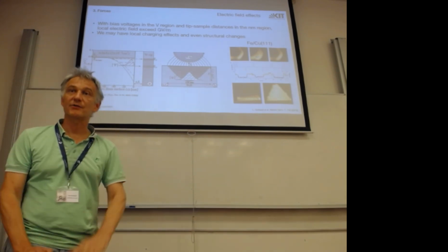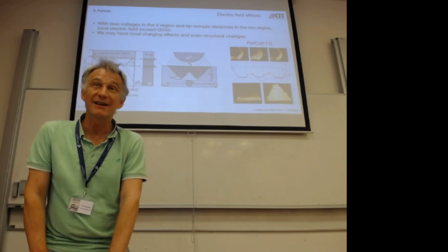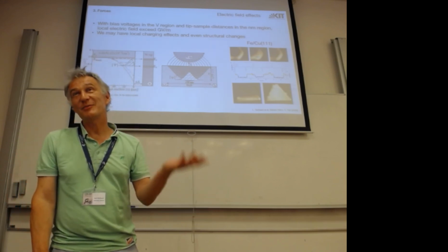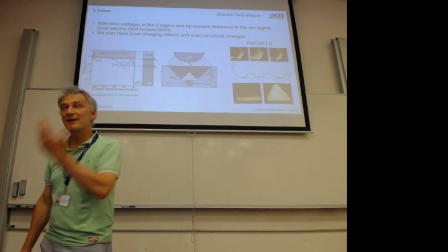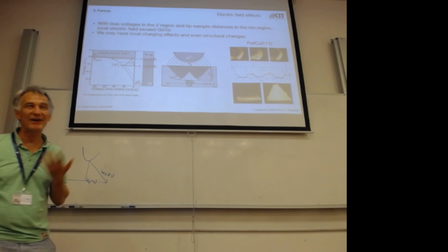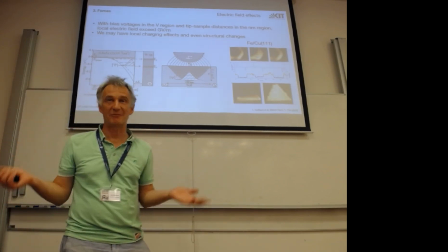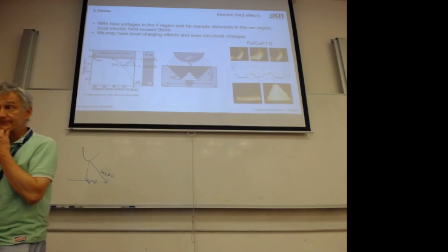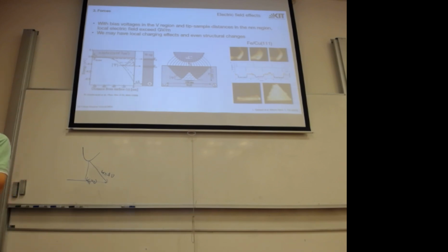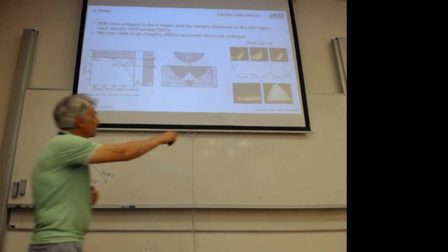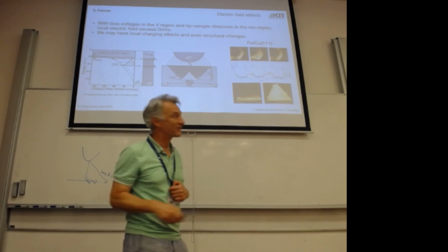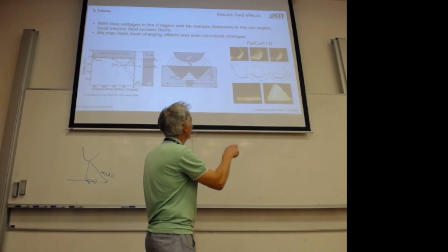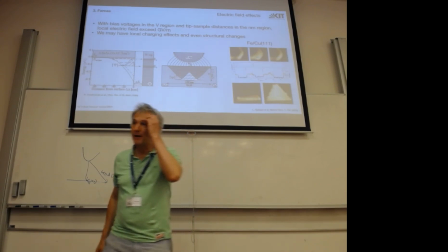Of course, there is magneto-electric coupling, but due to the electric field being a polar vector and magnetism being an axial vector, I cannot switch the direction of a magnetization, but I can switch the size of a magnetic moment. So this allows me to switch on and off ferromagnetism. By pulse, you mean actually changing the potential? Yes. So this is very small. I will put the slides online, but you see the time trace here. And I give like 1 point something volt and -2 volts. After each pulse, my structure changes.